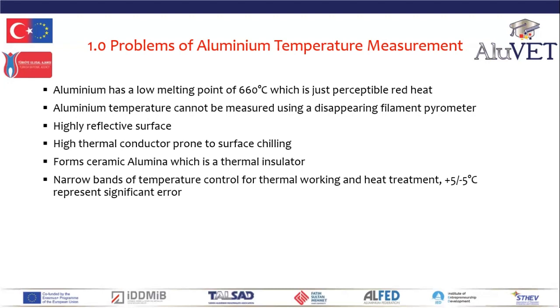Aluminium, even at elevated temperature, has a highly reflective surface. It appears silver, very, very reflective. Aluminium has high thermal conductivity, so its surface is prone to surface chilling. Aluminium in contact with air, oxygen, forms an oxide, alumina, which is a ceramic, a thermal insulator. Alumina has totally different thermal characteristics to those of the underlying parent aluminium metal. And heat treatment, particularly aerospace heat treatment and hot working, requires very, very tight, narrow bands of temperature control.